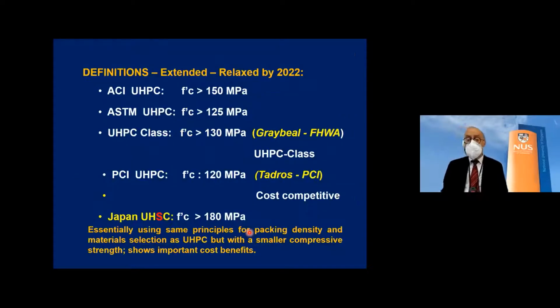Now, I would like to immediately say that the ACI definition was 2018. By 2022, we have had some relaxation, I would say, of some of these requirements. First, ASTM, in one of its recent standards, I can't remember the number, specified that UHPC should be more than 125 megapascal. So that's a little bit of relaxation with respect to 150.